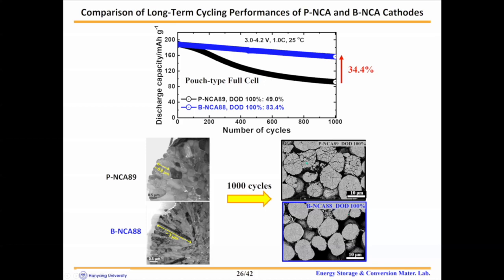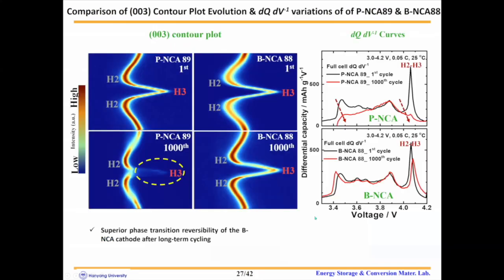And as you can see from the cross-sectional SEM image, after 1,000 cycles, the PNCA cathode particle was nearly pulverized into several segments, whereas the BNCA cathode maintained its original particle integrity. The superior cycling stability of the BNCA was further confirmed by in-situ XRD measurement before and after 1,000 cycles. As you can see, the BNCA cathode demonstrates smooth phase transitions after long-term cycling, whereas the H3 phase is not observed in the pristine PNCA cathode after 1,000 cycles.